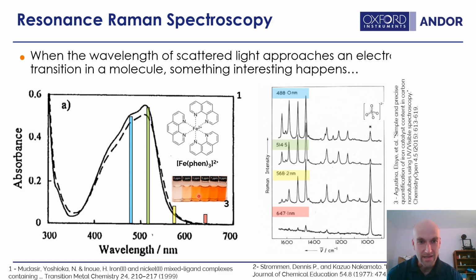You can see an inset here. Here's what the solution of this actually looks like as you increase the molarity. And unsurprisingly, it's a red solution, because the red light is allowed to pass unhindered through there without getting absorbed and either scattered somewhere else or thermalized and turned into vibrations or heat. So the question becomes, we've been working off resonance, non-resonant Raman spectra that are purely about interactions with molecular vibrations without bringing excited electronic states into there. So what happens as we push further and closer into that electronic transition resonance, or into that absorption band here?